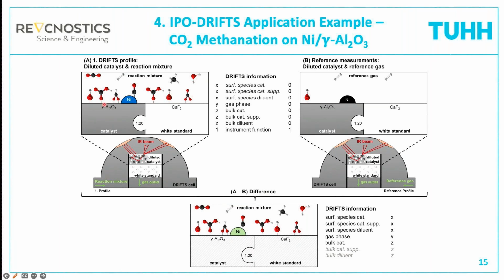And then we have the catalyst support, gamma alumina. This will definitely absorb IR light, and also the calcium fluoride to some extent will absorb the IR light. And in principle, this could change if we go through the reactor. It's very unlikely that gamma alumina and calcium fluoride will change, but in principle, if this was another support, it could also happen that this changes. That's why it's called Z. And then we have the instrument function, which should not change, but we gave it a 1. And now we perform this measurement under the reference gas hydrogen. Then we have only the instrument function, and everything else will be basically constant. And when we calculate now the difference between A and B, then you see we are left with all the changing things, X, Y, and Z, and the instrument function cancels out.